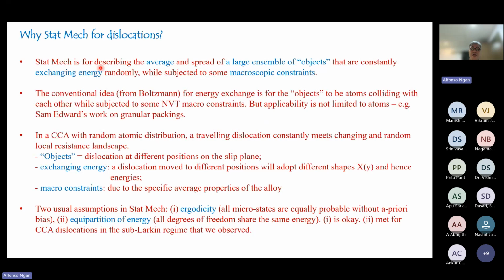Well, StatMech is for describing the average and spread of a large ensemble of objects, which are constantly exchanging energy between one another, and there are some macroscopic constraints applied. So the conventional idea from Boltzmann is energy exchanges for atoms or molecules colliding, right? And we can then subject them to some macro constraints such as NVT or NPT. Bending that concept to dislocations, the objects in this case would be the dislocations. And you can imagine that you may be talking about a single dislocation, but it is moved to different positions on the slip plane.